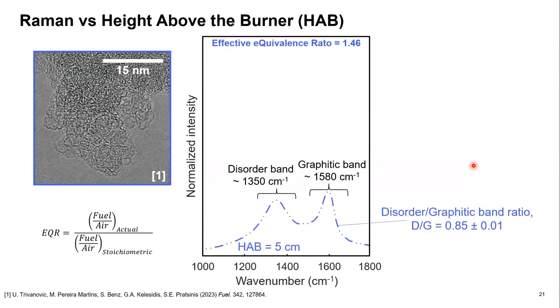The next thing that we looked at was the nanostructure of the soot. So we wanted to understand what was happening also on the inside of the particles and not just on the outside. And we did this with Raman spectroscopy. So here we see a characteristic Raman spectrum of soot, and we have these two peaks, first the disorder band and then the graphitic band.